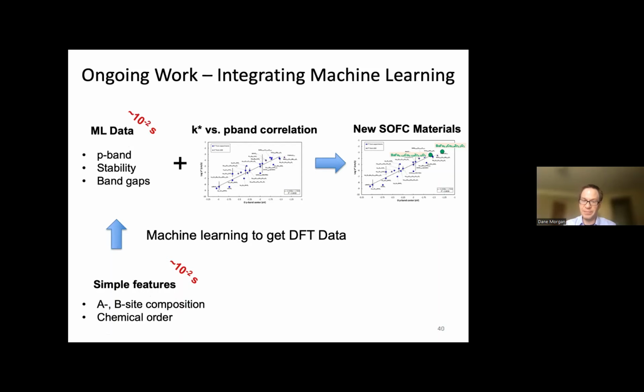So that's what we did. We basically machine learned a relationship between these elemental properties, like A and B site composition properties, and these DFT data, and we replace this DFT data with machine learned data. I haven't done all of this yet, but that's the idea. And suddenly this goes from taking 10 to the 5th seconds to taking only a fraction of a second.